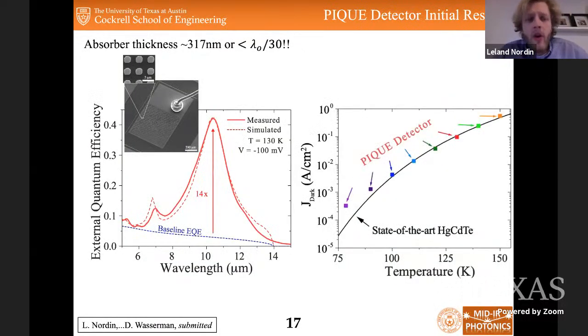So same story as the RCE detectors. We fabricated them into full devices and performed spectral characterization and external quantum efficiency. And then I also have a nice SEM micrograph in the top left inset of our external quantum efficiency plot. And you can see we're able to realize around 42% quantum efficiency in only a 317 nanometer absorber, which was much, much, much smaller than the free space wavelength of light. And it amounts to about a 14x enhancement. So over an order of magnitude enhancement in EQE relative to if we just grew this same thickness of absorber, this detector, on a non-plasmonic ground plane with no grating couplers.